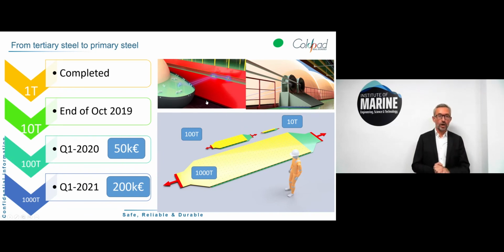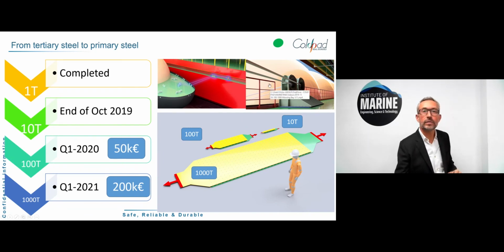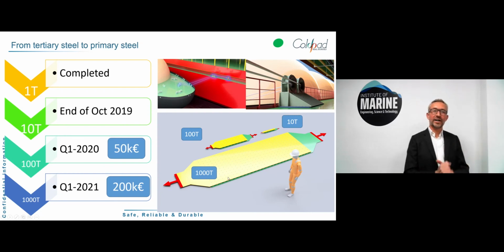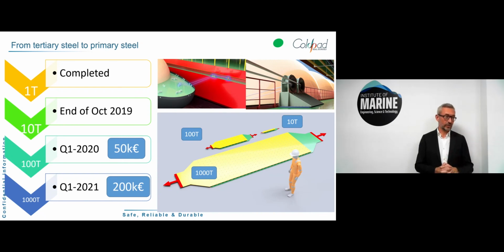And the next step will be 100 tons, and the step further will be 1000 tons. So already 100 tons, I'm sure this is a world first, to transfer 100 tons through a bonded connection. For the 10 ton capacity, we demonstrated we could achieve 10 tons. After 10 tons, we had a failure in 1 cycle, but not in the bonded line, in the threaded rod.